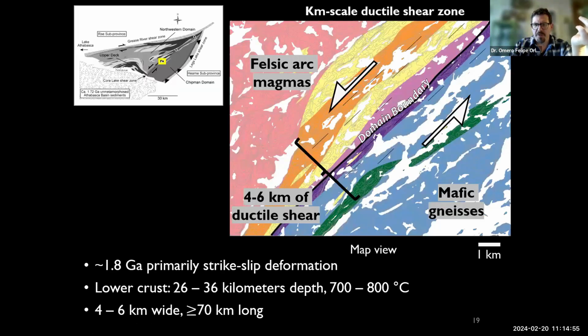And so here's a much smaller field scale map with the lithologies actually colorized. And again, it doesn't really matter that you know what the lithologies are, beyond understanding that the blue half of this is much more mafic than the northwestern side of it. And so this structure of the Cora Lake Shear Zone has been dated through synkinematic monazites and other constraints to be about 1.8 Ga. Long dead, long dead.